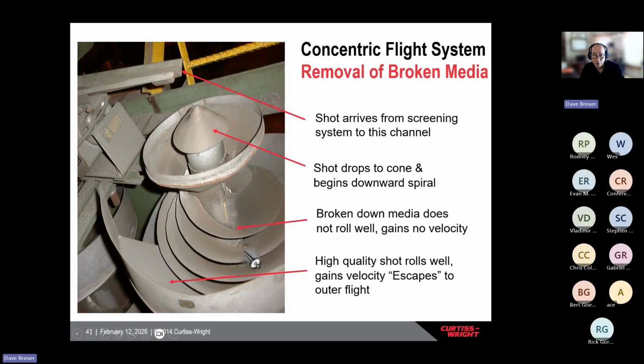A good high quality shot will gain enough velocity to go from the inner flight to the outer flight. That shot that reaches the outer flight we reuse because it has a good shape, but the broken down shot doesn't roll very well, so it stays on the inner flight, and we throw that away or recycle it - bottom line, we don't reuse that shot.